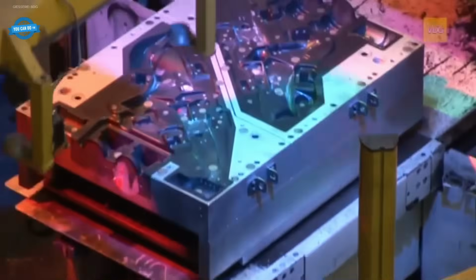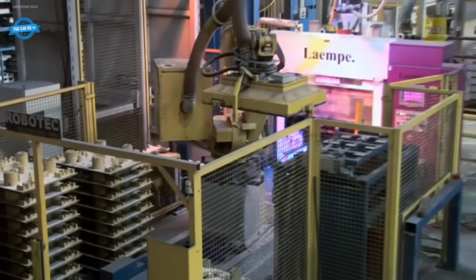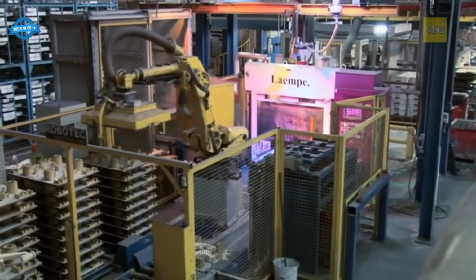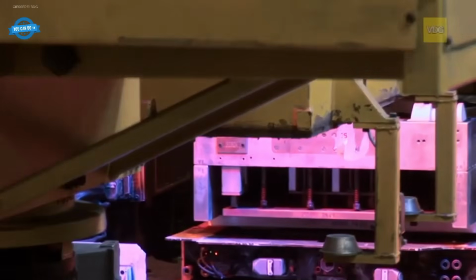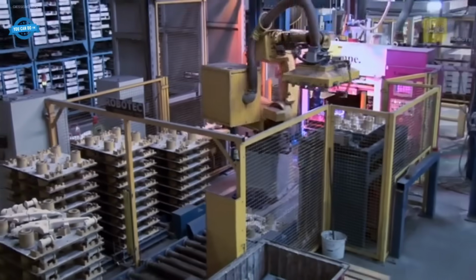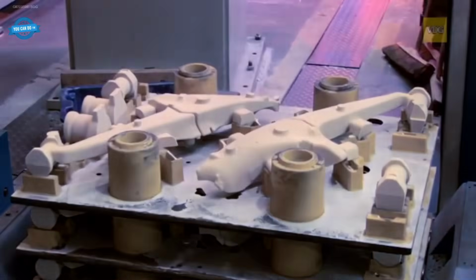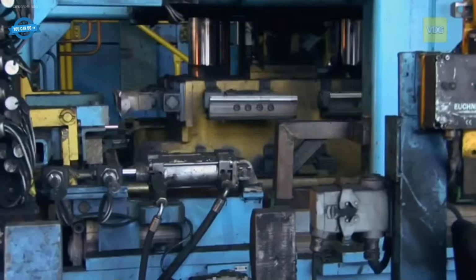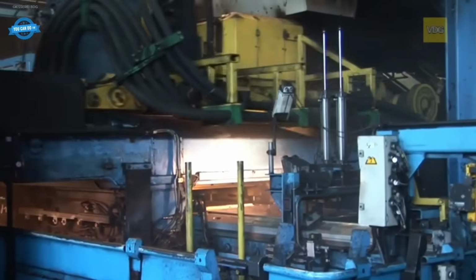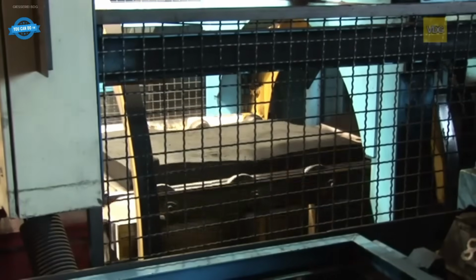Metallurgical quality is confirmed through spectrographic analysis. Samples taken from the melt are analyzed in real time to verify chemical composition. Microstructure is examined under a microscope after etching polished sections. For mechanical validation, tensile bars are cast integrally and tested on universal machines for strength, yield, and elongation values.